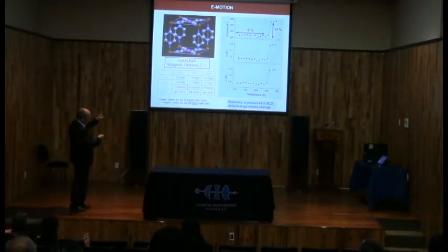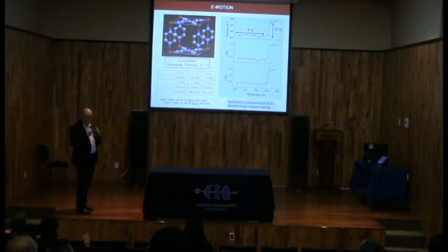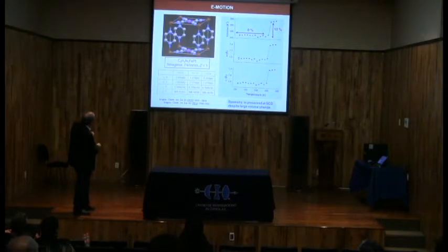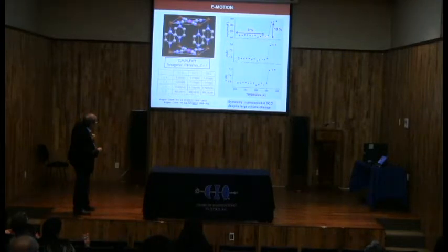So then, if you look in classical way by X-ray diffraction, this molecule here, you see that when you measure the crystallographic properties, this is the low spin, and this is the high spin. And this is the volume cell. You see that the volume cell of your system changes by 13%.